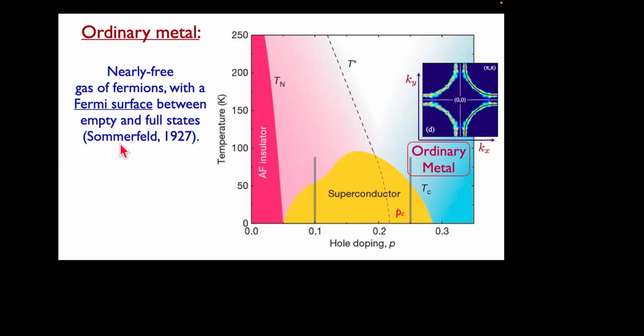So one of the main features of this theory is something we call the Fermi surface. So this is the boundary between the single particle states that are occupied and empty. So in a clean crystal, you can label the states by momentum. And so this is a measurement through a photo emission experiment of this boundary. So there's this boundary here between the occupied states, which are actually inside, and the empty states, which are outside of the electrons. So this was the Sommerfeld model of nearly free electrons.